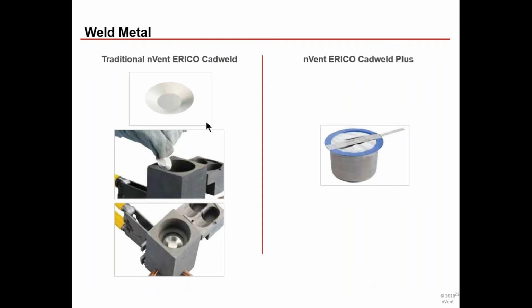If you're doing traditional, you have to use one of these discs. These discs basically allow a little bit of cook time. It's not long, but it holds up the weld material after it's been ignited just enough that the slag has the time to float to the top and the copper has time to float to the bottom. So you want to make sure that your little plug here is set correctly.